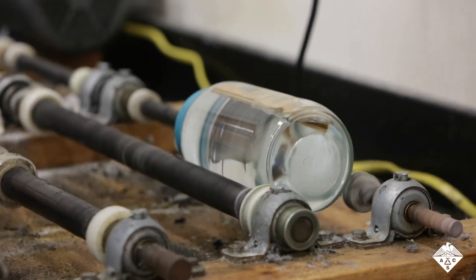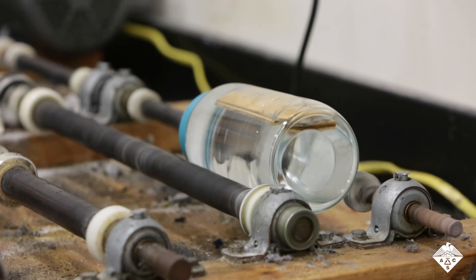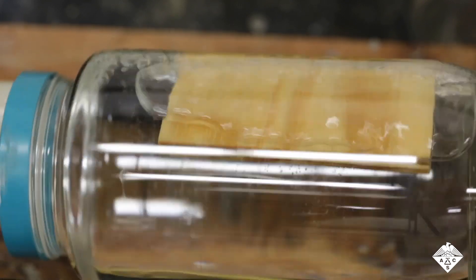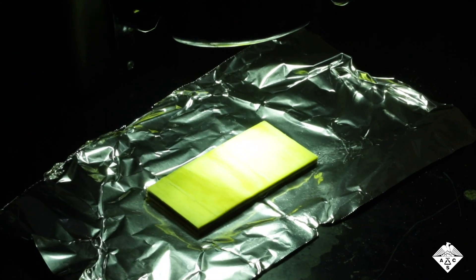The plywood was dipped in an aqueous solution containing a positively charged polymer polyethyleneimine (PEI), a monomer hydroxyethylmethacrylate phosphate (HMP), and a photoinitiator known as TPO. The plywood was then exposed to ultraviolet light for a few minutes.